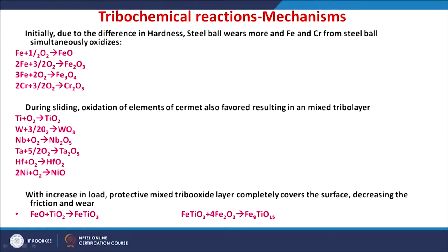The material removal from the cermet surface results in the oxidation of the elements from that material. So, we will have oxidation of the elements, for example, titanium gets oxidized, tungsten is oxidized, niobium is oxidized, tantalum is oxidized, hafnium oxides, nickel oxidizes. So, the oxidation of these elements of cermets is possible in the continuous process of sliding. Initially the iron oxide is formed, and then the hard iron oxide will abrade the cermet surface, and the elements from the cermet surface also get oxidized, and we will have oxides forming on the surface. But at higher loads, these oxide debris will be mixed and then compacted and form a tribolayer.